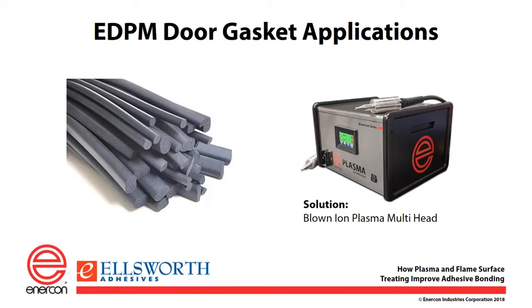Door gaskets, all the gaskets you see in your car, prior to using flame, they would generally use a solvent wipe and then a primer, but you can achieve better bonding and eliminate the primer and the solvent wipe by just using a blown ion onto the surface where you're going to put the adhesive in the gasket.